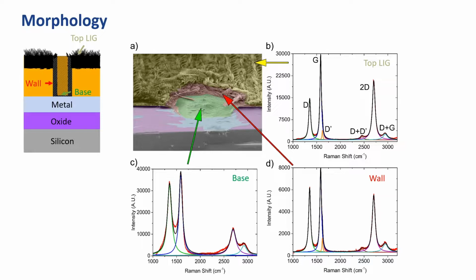The top surface is high quality laser-induced graphene, defined by its sharp 2D peak and low intensity D peak. The wall region has a more intense D peak than the top surface leg. However, the base of the plug displays more defective material, demonstrated by the convolution of the D and G peaks in addition to the broadening and attenuation of the 2D peak. Considering this alongside the fluorescence and electron micrographs, a more complete picture of the continuous LIG contact from the top surface down through the wall to a base beneath which there is a metallic layer is established.